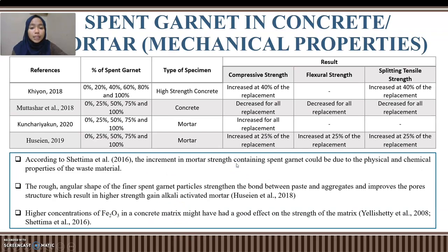Next, I will discuss about the mechanical properties of the spent garnet in concrete or the mortar. We can see on the table we have 4 researchers that report the result of the mechanical properties of spent garnet in concrete and mortar. For Khiyon 2018, replacing different percent from the other research, Khiyon made high strength concrete. The result from Khiyon research, it increased at 40% for the compressive strength and splitting tensile strength.